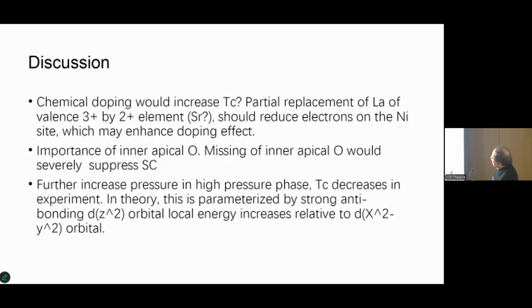The other is the importance of the inner apical oxygen, because of the similarity with the cuprate. For the doped or self-doped Mott insulator, it's closely related to this inner apical oxygen to bond the top and the bottom nickel sites. So missing inner apical oxygen would severely suppress superconductivity. And experimentally, they report this, the inner apical oxygen is terribly important. If a lot is missing, they don't get a superconductor.